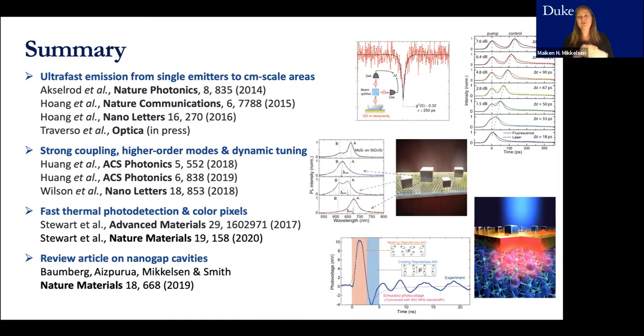And in some cases, when we want it also smooth, we might do something called template stripping, where we evaporate the metal on top of a very smooth silicon wafer, and then we can peel it off, and we can use that as our starting surface. Then we can get RMS roughnesses down to like 0.3 nanometers as measured by AFM. So smoother is definitely good.